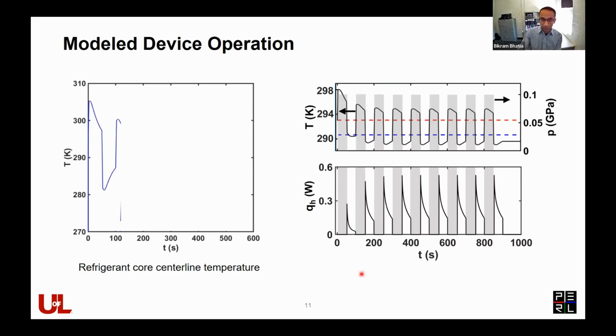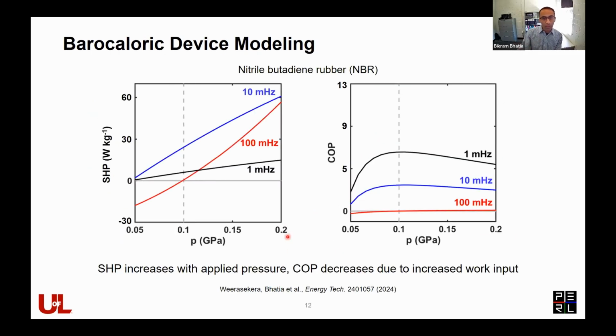So using this, we can figure out what the specific heating power and COP of the heat pump is as a function of applied pressure, which is shown here. So we picked a material known as nitrile butadiene rubber, which is a common elastomer, widely available, low cost, as our material of choice, which already had experimental results reported in the literature. And so what we see in these plots is, if you look at the specific heating power, as you apply more and more pressure, you can imagine the temperature change or the entropy change of the material increases. And so that causes the specific heating power to increase with applied pressure.